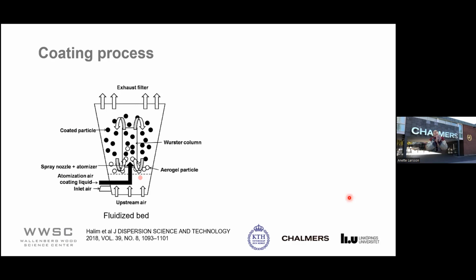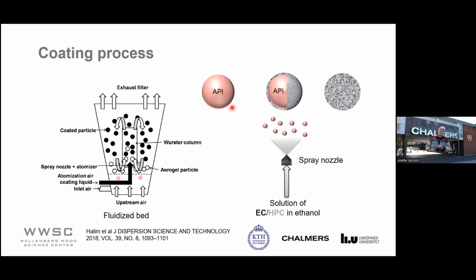When you apply the coatings, one can do it in different ways. If you have pellets, it's very common that you use a fluidized bed. And I don't know how much you know about fluidized beds, but in fluidized beds, you have a pressure of air and you have the particles, and they start to dance in this system, going up and down, around like this. And they pass then the Wurster column. And here we have a spray nozzle. And so here is the core with the API, and then we have a spray nozzle that sprays small droplets to the surface, and these droplets flow out and wet the surface and dry.